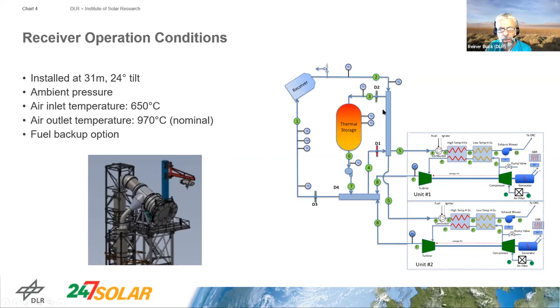And the way it operates, remember the receiver is at ambient pressure. Then of course, when it goes down to the heat exchanger, which heats the inlet air to the turbine, you have additional pressure drop. Eventually, you can introduce also fuel here to heat up if there is not enough energy coming from the sun, from the receiver. And then the additional component is this exhaust blower, which is controlling, by some minor suction pressure, that the receiver is always at ambient pressure.